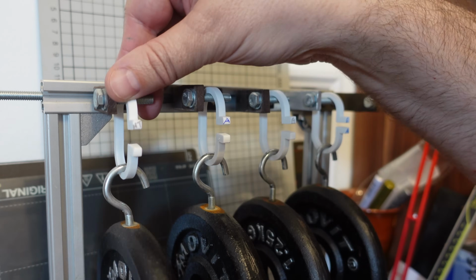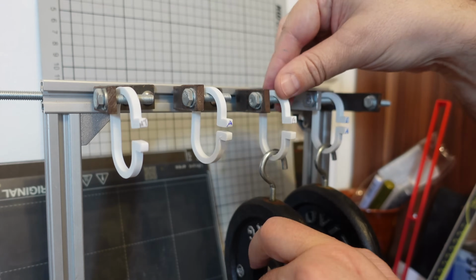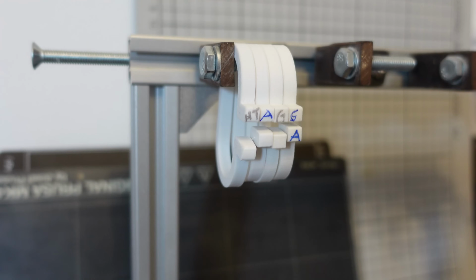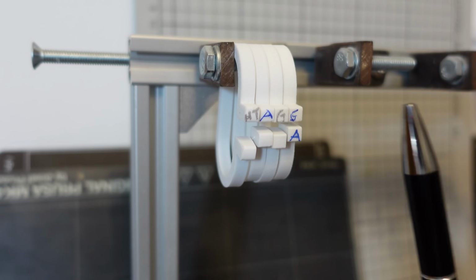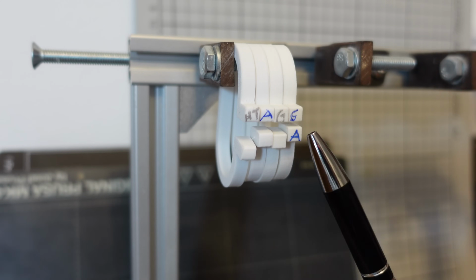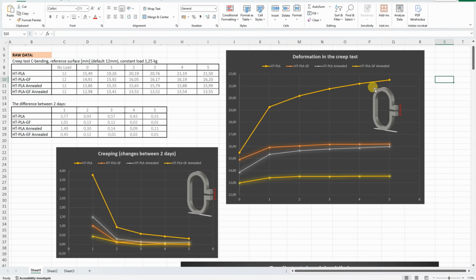Removing of the load. It's quite obvious that the glass fiber helps against the creeping, but also the annealing too. But let's see the numbers. On this graph we can see the deformation, the distance between two reference surfaces. And we can see more deformation on the HT-PLA compared to the glass fiber version, but we can also see that annealing helped. But this test is not about the bending, but about the creeping.